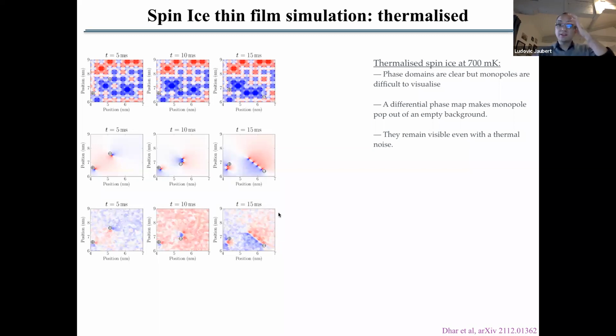Now, this is one aspect. So here it has shown that you can see monopoles as being the end of this Dirac string. So when a monopole moves, it leaves a wake of flipped spins behind. These flipped spins correspond to Dirac strings, and these Dirac strings correspond to a very sharp discontinuity of the phase map. And so when you look at the end of these Dirac strings, it corresponds to the monopoles that you can measure with this differential phase map. But now, the interesting thing that we noticed is what happens when you close these Dirac strings.